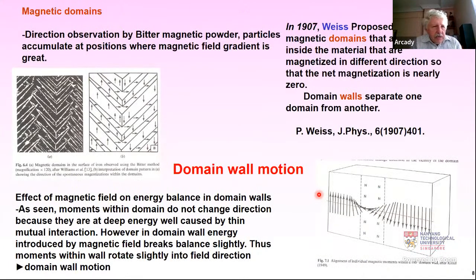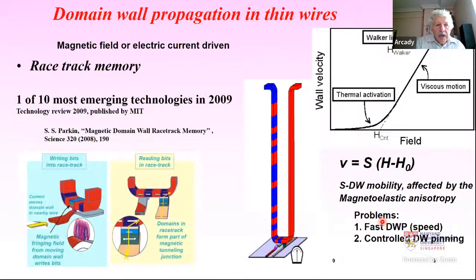This is just for educational purposes. Magnetic domains were reported more than 100 years ago. And what is important is that on the application of a magnetic field, the domain wall, which separates different domains or different magnetization orientations, can move. In our case at least, we will deal with the so-called viscous regime, where the domain wall velocity is given by a linear dependence on magnetic field, because above some magnetic field there is some kind of Walker behavior, quite complex, and below there is an important contribution of thermal activation.